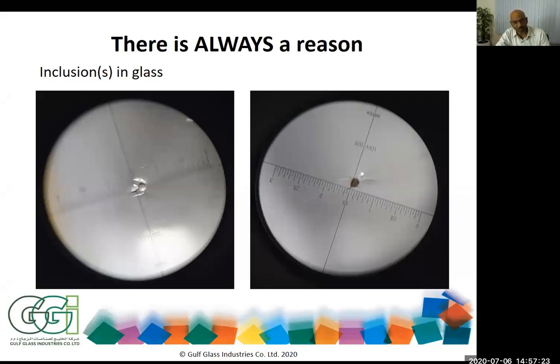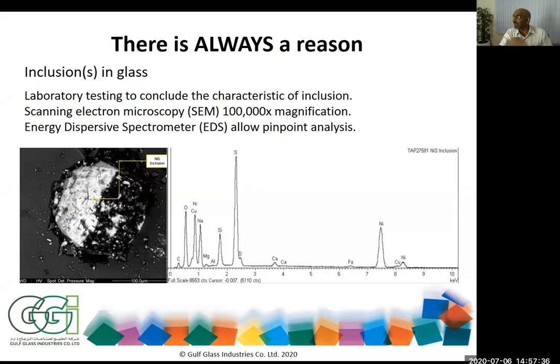As GGI, we do not say that it is an inclusion and we do not comment on it. We say it is a possibility that it could be a nickel sulfide inclusion, but we are not sure. How can we be sure? By doing laboratory testing to conclude the characteristics of the inclusion. So SEM analysis has to be done in a laboratory, and EDS, which is pinpointing the analysis. As you can see from the graph, this is one of the inclusions that was sent to a lab in Europe, and they did the scanning of it. You can see the peaks which show that it is a nickel sulfide inclusion. So that's the way that you can 100% claim that it is a nickel sulfide inclusion.